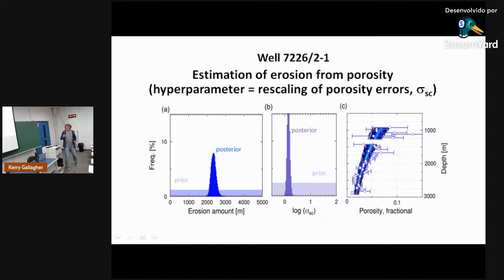So if the data are too precise, then we try to overfit them, and we can get a bit confused as to what's a reasonable model. So one way of dealing with that is to say the data are not as good as we think they are, and let's find out how not good they are. So this is a scaling factor that multiplies the input errors on the porosity to try and find a more consistent model for all of the data. Okay, so this is again a nuisance parameter. We don't really care about that, but it's useful to be able to estimate it.